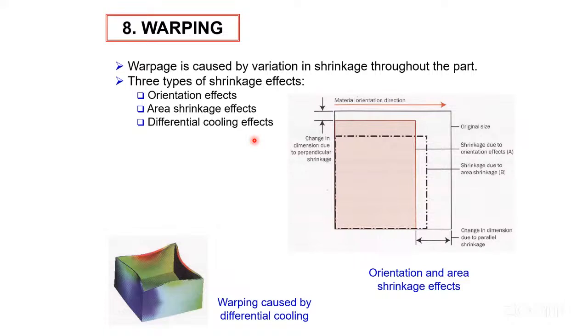And you have seen many jumbo articles also, or jumbo crates, jumbo trays. There is a lot of variation in the thickness, or maybe the side gets bulky at the center. If you observe here in this case, here also is the material orientation direction, this orientation here. This is the original article. See, this is the original article here. But after shrinking, it becomes like this. After shrinking, a lot of shrinkage is there, maybe 5 millimeter or maybe even 20 millimeter. Why does this happen? Why will such shrinkage be observed? Because of the orientation.